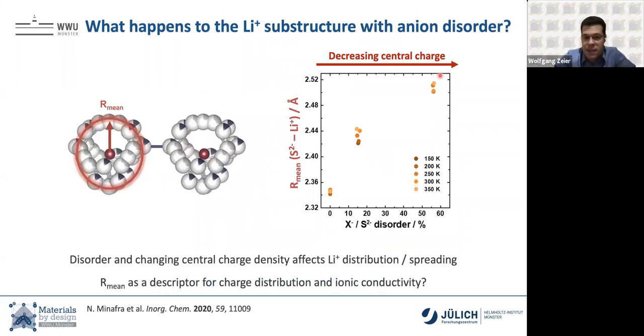Why? Well, I think this is fairly simple. We have a rearrangement of anionic charges. So at 0% disorder, it's all S2- in the center of the cage, and S2- will be very Coulombically attractive to the lithium. Now we turn on the disorder. The central anionic charge decreases. It's less negative because now there's a bromide on it. So there's less Coulombic attraction, and they can expand. And if we put the chloride on it, they expand even more.